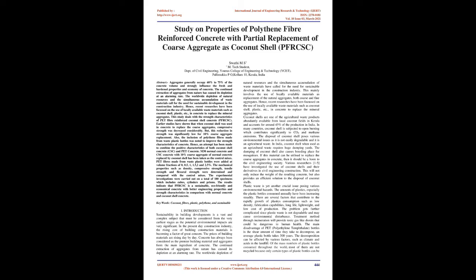Earlier studies have shown that when coconut shell was used in concrete to replace the coarse aggregates, compressive strength was decreased considerably. But this reduction in strength was significantly low for 10% coarse aggregate replacement. Also, the inclusion of polythene fibers made from waste plastic bottles was noted to improve the strength characteristics of concrete. Hence, an attempt has been made to combine the positive characteristics of both coconut shell concrete, CSC, and PET concrete.